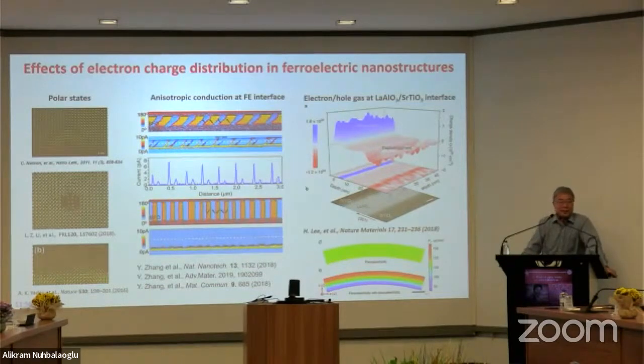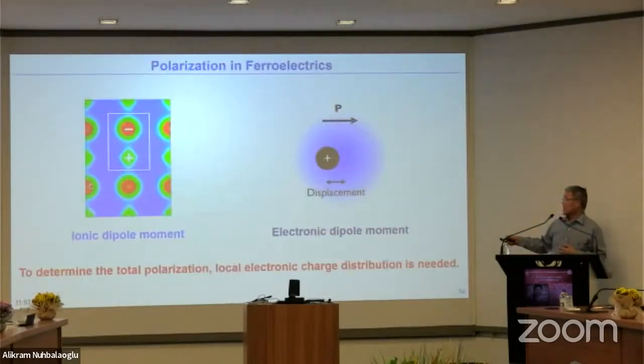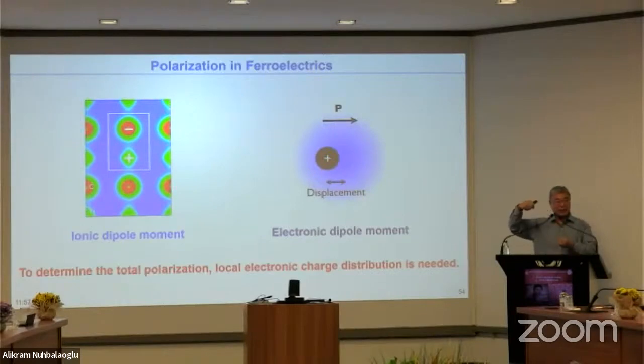Yes, so the charge at the interface is very important, to directly see this kind of electronic charge at the interface. And also in the polarization measurement, the quantitative method that we developed to measure the dipole moment from unit cell to unit cell, we only use ionic displacement because we have not yet considered the electronic charge. So the polarization referred to should consist of both ionic displacement and also electronic displacement. Any neutral atoms put in the electric field will have induced electronic polarization. So they should be considered.